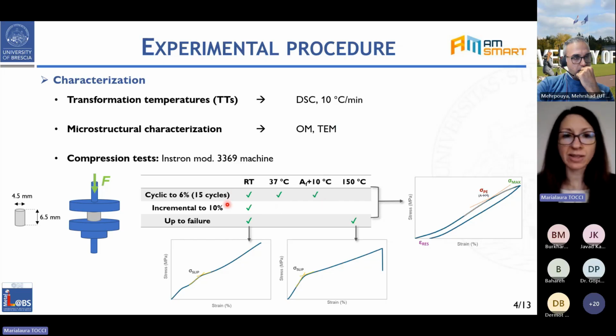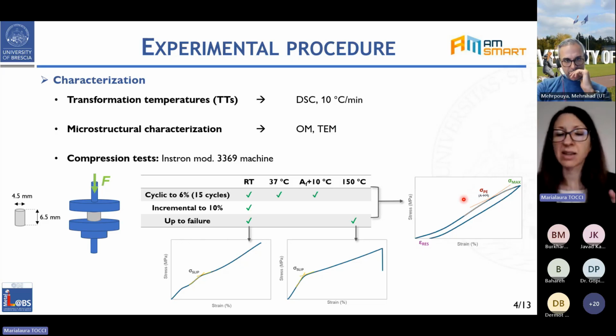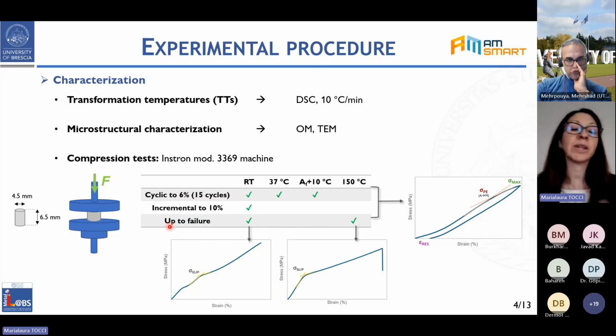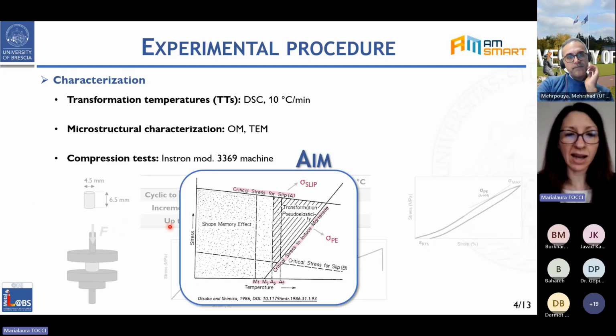And from the curves of this test, we calculated the maximum stress reached, the pseudoelastic stress as the critical stress that induced the martensitic transformation, and the residual strain. Finally, in order to build the stress temperature diagram, we also needed to perform tests up to failure, and in this case, temperature was set from room temperature to 150 degrees. These high temperatures were selected simply to be able to build graphs similar to what we can see here, a stress temperature diagram, in order to identify the superelastic window for the material after the different heat treatments.